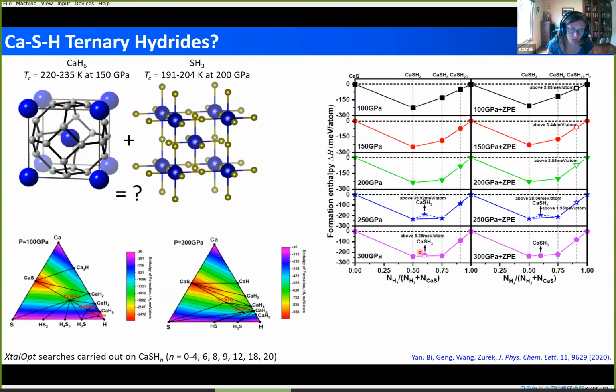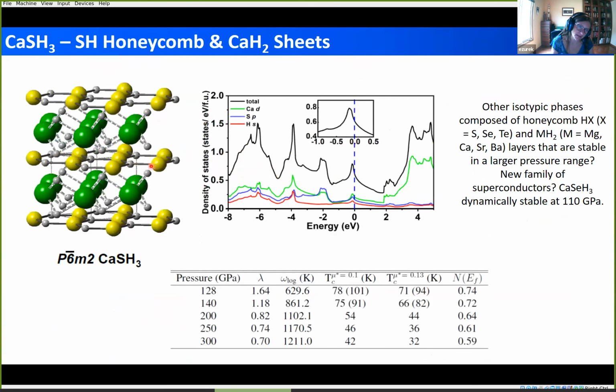There was only really one deviation, and that's this calcium sulfur H3 phase, which was found to lie on the convex hull we calculated at very high pressure when the zero-point energy was considered. Here I show the phase. What's interesting is it basically looks like a two-dimensional version of H3S, in the sense that you have these honeycomb sheets made up of hydrogen sulfur with a calcium H2 spacer in between.